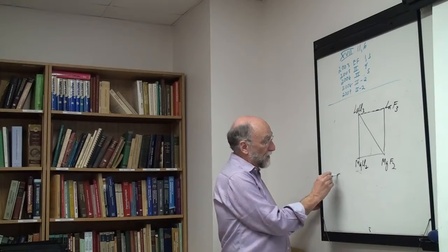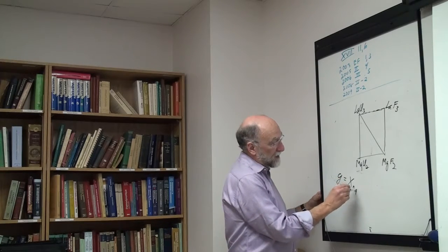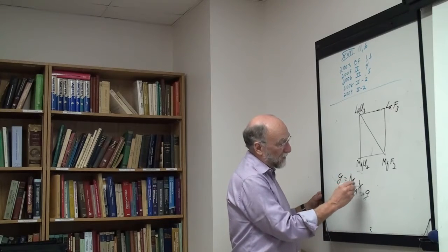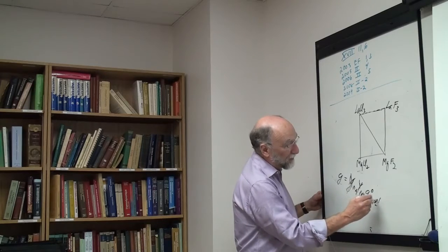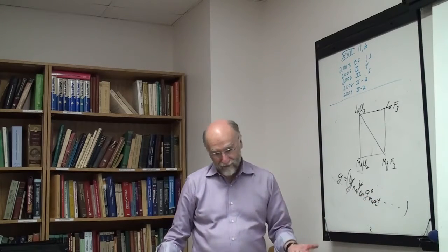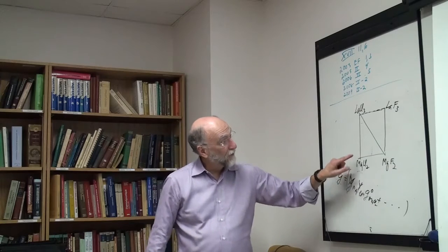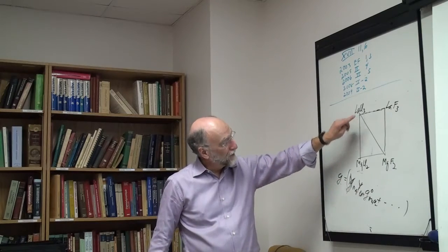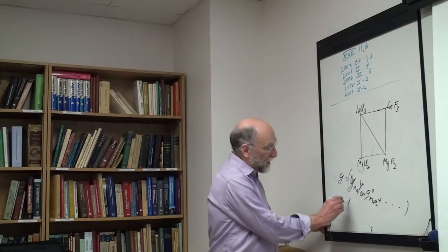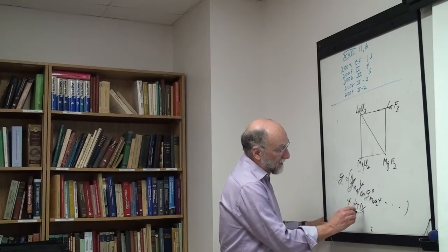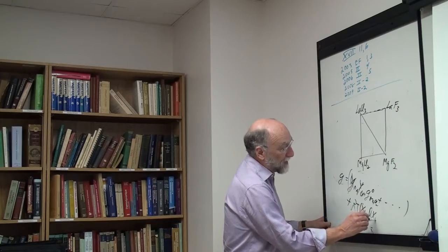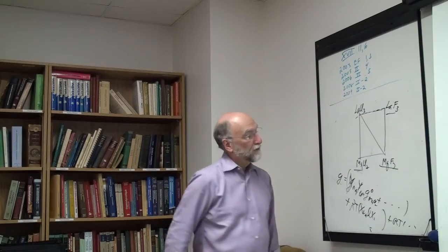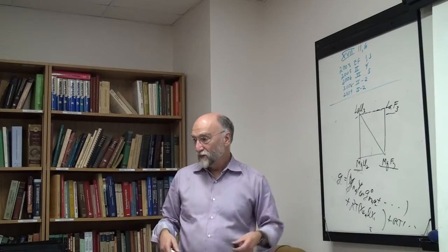Okay, and the model for the Gibbs energy is Y magnesium, Y chlorine, G naught magnesium chloride, plus you use the sublattice model. You have the Y magnesium, Y chlorine, G naught magnesium chloride, plus Y lanthanum, Y chlorine times G naught LaCl3, plus you have the RT, and then you have the X lanthanum ln X, the mixing of the magnesium and lanthanum on their sublattices, plus the next term for the mixing of the fluorine and chlorine on their sublattices, the whole thing.